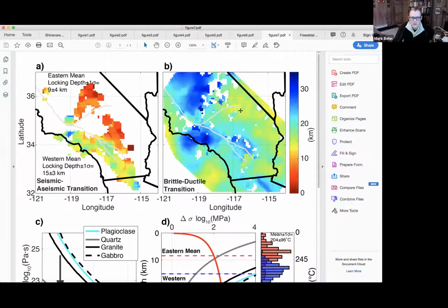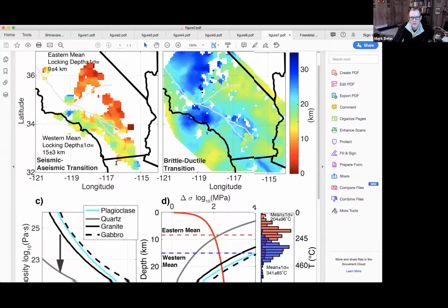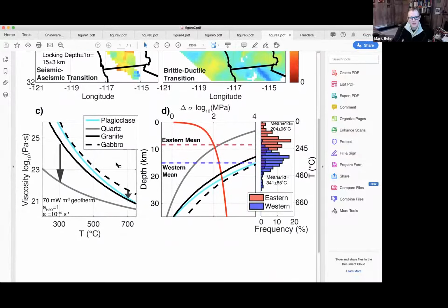But what is really interesting in Southern California is that the last thing Billy looked at was how his predictions of where the brittle ductile transition is compare to the seismic aseismic transition based on locking depths. And so the red is showing the locking depth, and there's this relatively distinct change from a shallow locking depth to the east to a deeper locking depth to the west. And we looked at that in comparison to predictions of the viscosity structures.